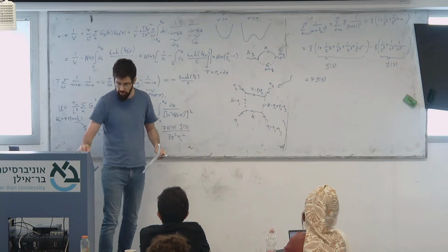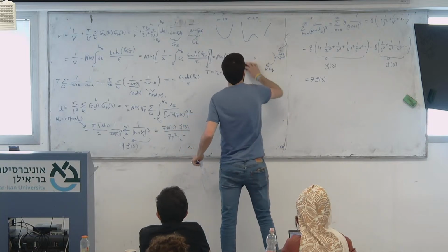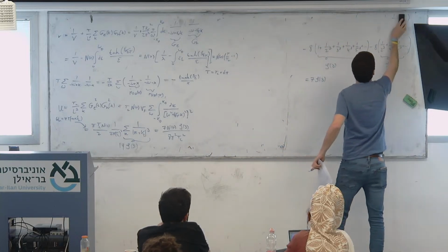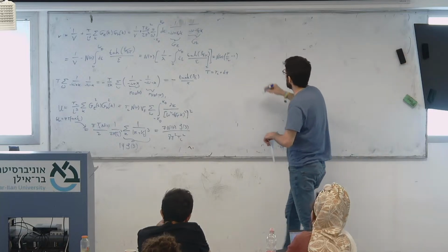So then this u comes out to be 7 N of 0 zeta of 3 divided by 8 pi squared Tc squared. Okay, so what does this tell me? Then I can already do the specific heat. And this year probably I'll have to give up on the... Okay, we'll try to do also the coherence length. We'll do that in a second.